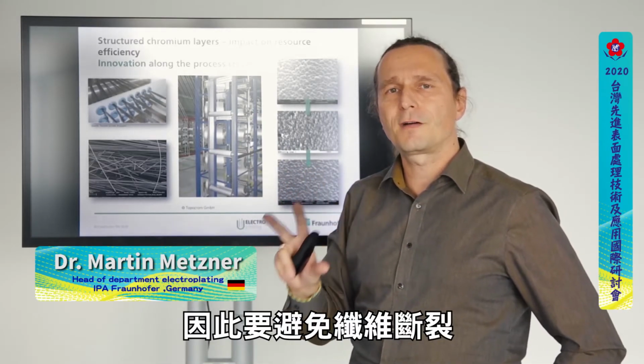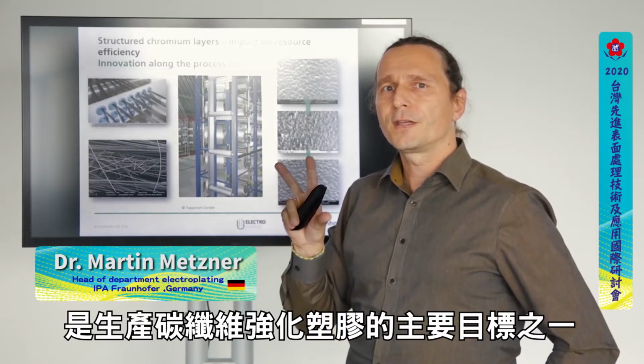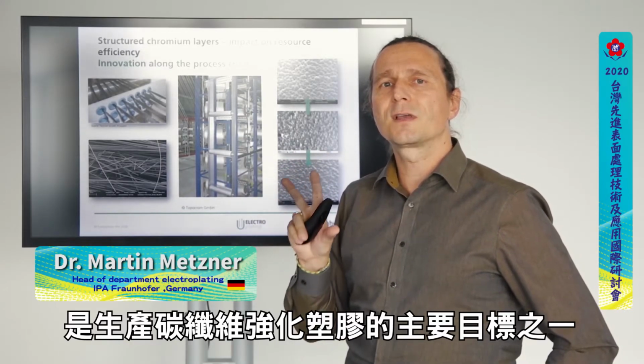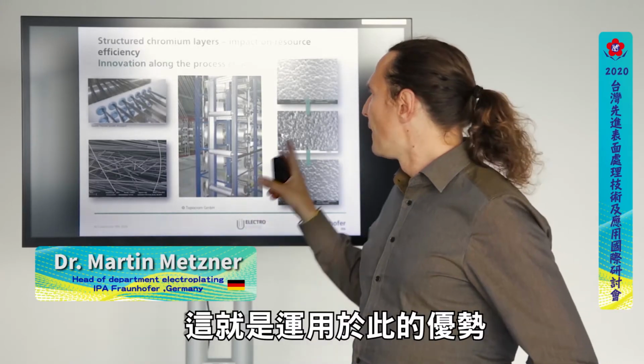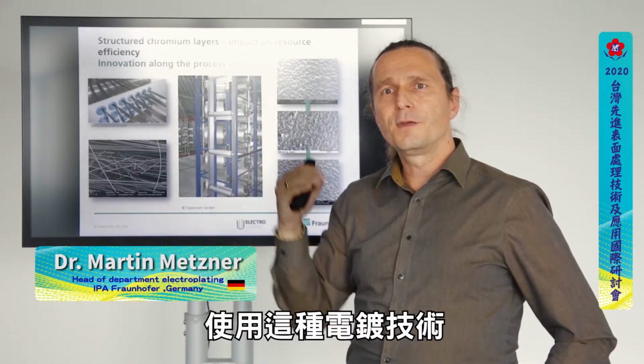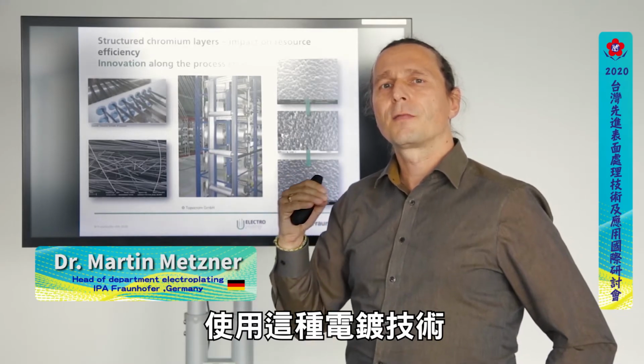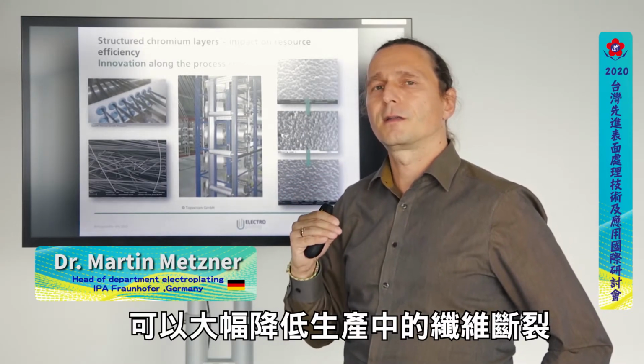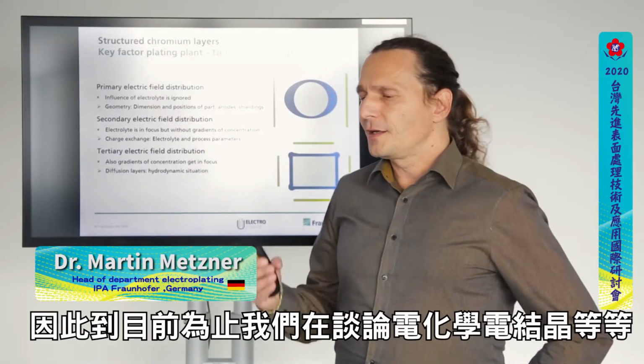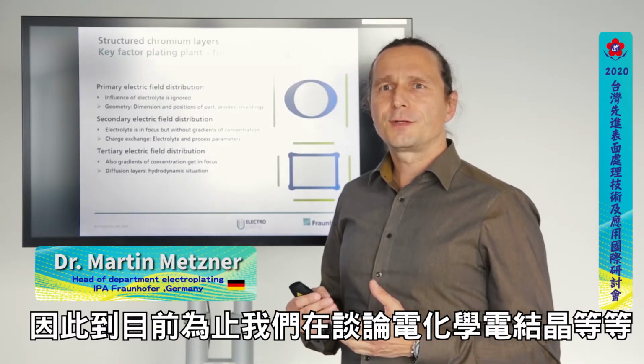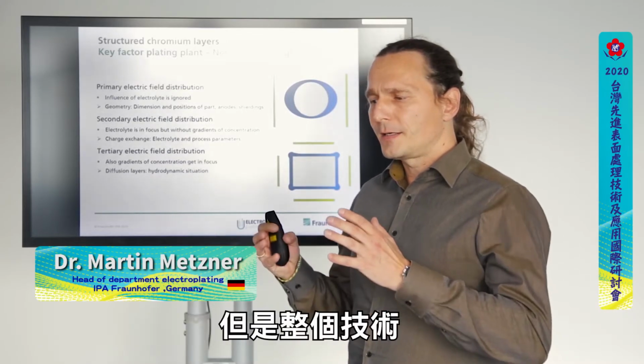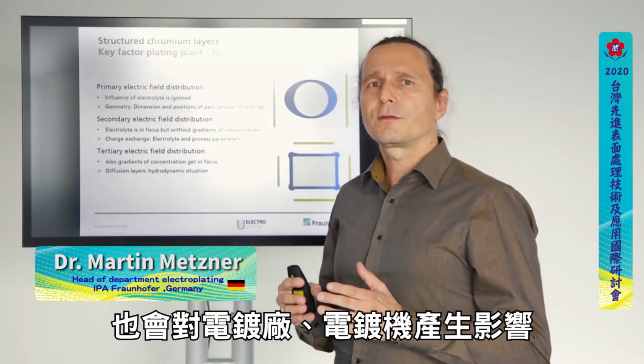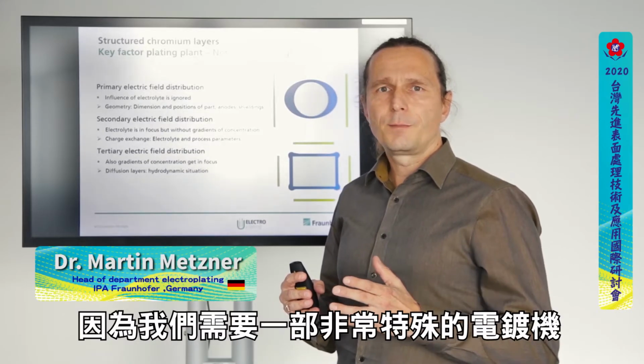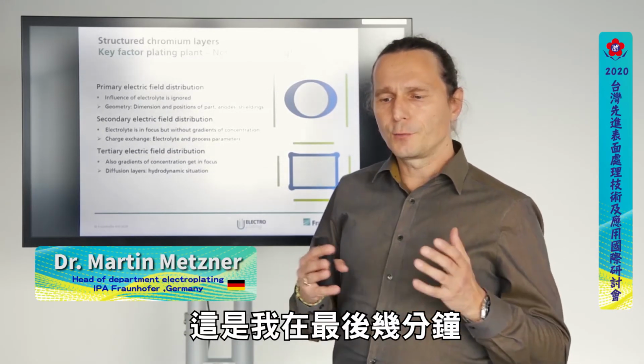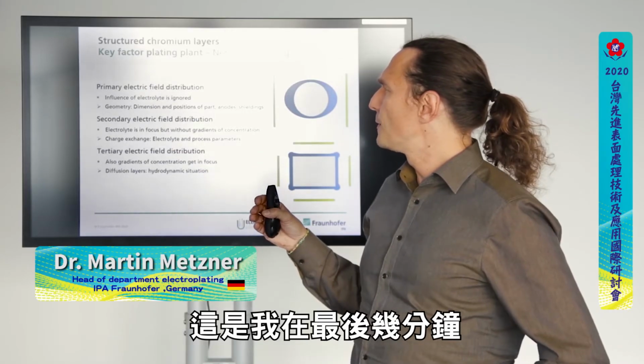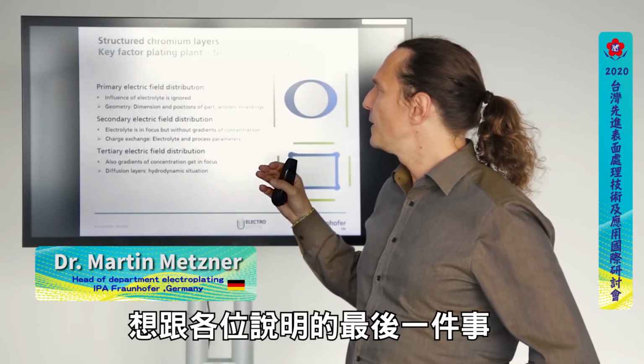So the breaking of the fiber, to avoid the breaking of the fiber, is one of the main targets when you produce carbon fiber reinforced plastic. And this is the advantage in here, that with this surface technology we can bring down the breaking of the fiber significantly in production. So until now we were talking a lot about electrochemistry, electrocrystallization and everything, but the whole technology also has impact on the plating plant, the plating machine, because we need a very special plating machine. And the reason for this is the thing I want to talk about for you in the last minutes.